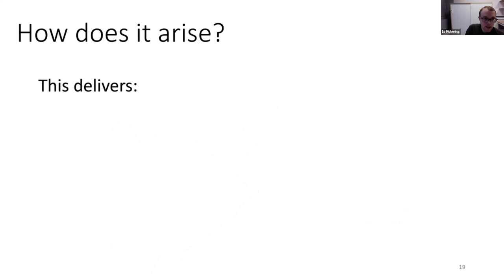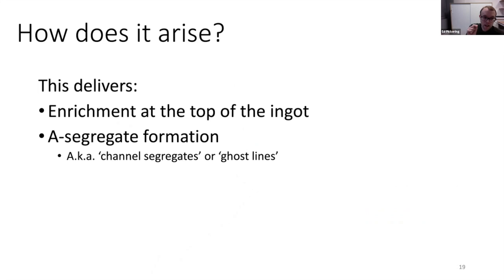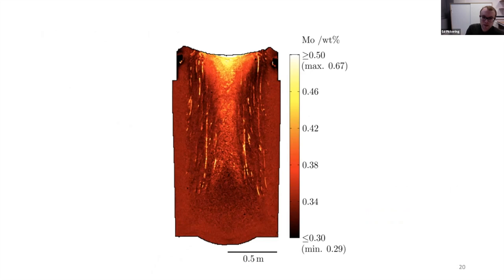And this delivers a few things. Firstly, enrichment at the top of the ingot, and secondly, A-segregate formation. These are also called channel segregates or ghost lines. If you look at an ingot here, you get that enrichment at the top because all the enriched liquid floats. In this particular case, it does anyway. Sometimes it sinks, but a lot of the time, because it's enriched in carbon and silicon, it floats. And you also get these ghost lines forming. So we get these A-segregates forming, which are these channels of liquid.